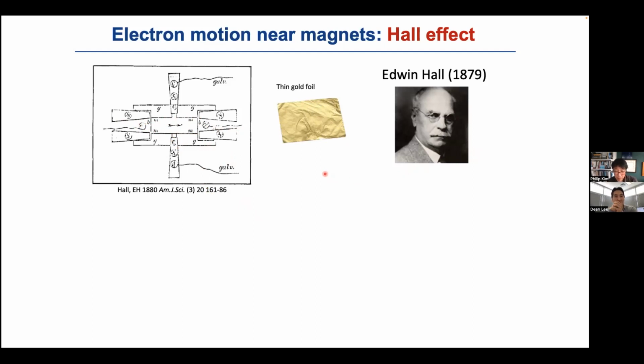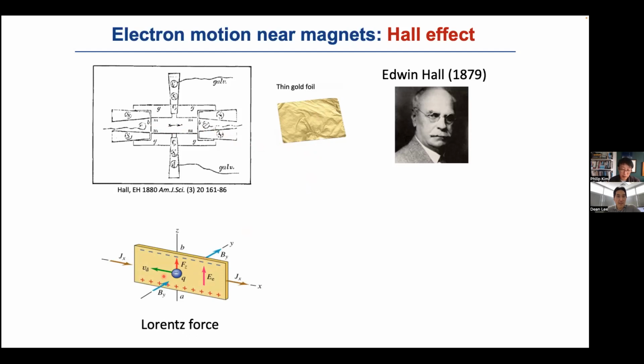One important problem he had to solve was to see this deflecting effect clearly. It turns out he needed a really thin object to carry the current through. Remember, this was the middle of the 19th century, so there's no graphene and no semiconductors. The way he came up with was to make a gold foil really thin. Because gold is a precious metal, people knew how to engineer a thin foil. Using this thin gold foil and applying the magnetic field in the normal direction of the foil, he could successfully measure the voltage developed across the current direction, which is what we call the Hall effect.